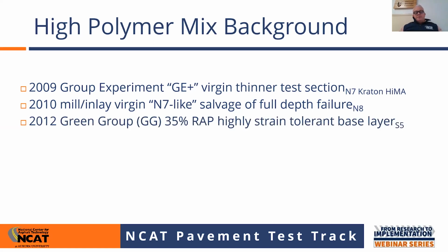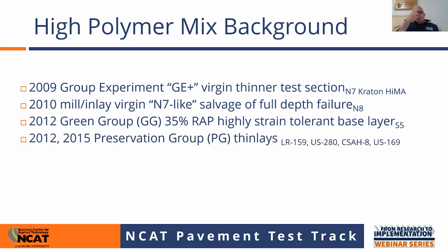In 2012, based on those successes, we built what we called at the time the Green Group Experiment. These group experiments are multi-state collaborations. Within that experiment, we had a high RAP focused test section that had a 35% RAP base layer with HiMA binder for the purpose of being highly strain tolerant. And that section did really well. Also in 2012 and pushing forward into 2015, we had thin lays that we produced with HiMA binder on Lee Road 159 on US in 2012, and then on US 280 in 2015, and then County State Highway 8 and US 169 up in Minnesota in 2016.